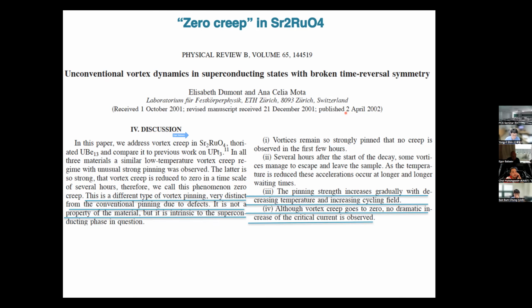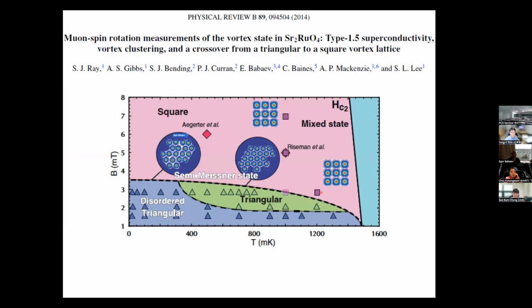They didn't talk about how inter-vortex forces are usually repulsive and so on, but it's precisely what should happen if your vortices form clusters and have attractive interaction. Then there is no vortex creep. They're not repelling each other out of the sample in zero field. They stick to each other, but we can also move these clusters easily by current. So this is not a self-contradictory statement as was thought before, that we may basically have zero creep and no increase in critical current.